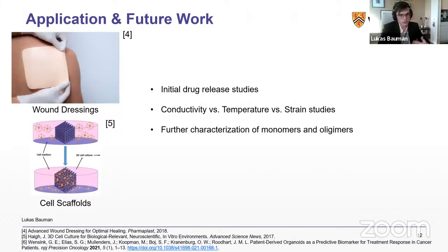Another option is to do cell scaffolds, where you would print a 3-dimensional scaffold that better mimics the human body, and then you can grow the cells on it. Through the swelling, as you cool down the temperature, the cells are more likely to de-adhere, which we've seen a lot with polyNIPAM. This would allow you to collect the cells and then do something like flow cytometry. So if you're measuring cell death when exposed to chemicals, you can expose them in situ like this, and then get them to be removed from the scaffold and actually properly count them.